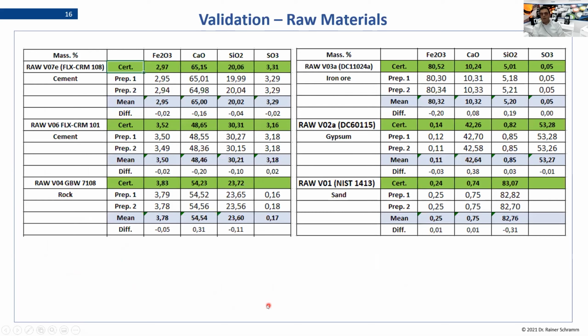Last but not least, here a summary for you, and you know that this will be uploaded on the YouTube channel, so you can also watch this later on in detail. And this is a comparison for different materials like cement, a rock sample, iron ore, gypsum, and sand, also fused at different temperatures, but all measured in the same calibration, and the maximum deviation we see from the certified values is here 0.4%. All the rest is in a lower range and absolutely in the range which is typical for very high precision analysis.